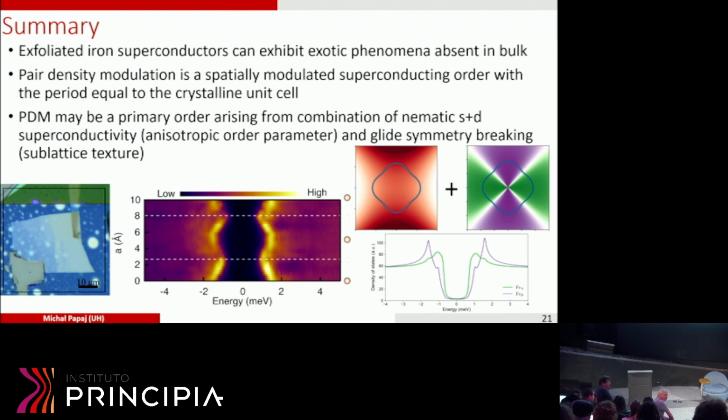I wouldn't say clear. There is some evidence, but I would invite more experiments to prove or disprove whatever I'm saying here. Why did you specifically choose the relative phase of these to just be S plus D? If we had S plus ID, in this case, I don't think we would see this modulation, because the absolute value at the two iron sublattices wouldn't be different.